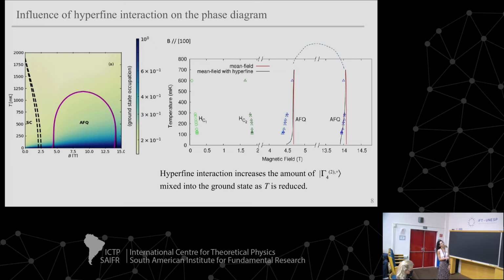But this one already looked a bit different. So if we match the high temperature data points, we could already see that this phase boundary was deviating from the mean field phase boundary. So we wanted to explore a little bit and go to lower temperature to see if our prediction of hyperfine modification of this phase boundary was true, but also what else happens down here.